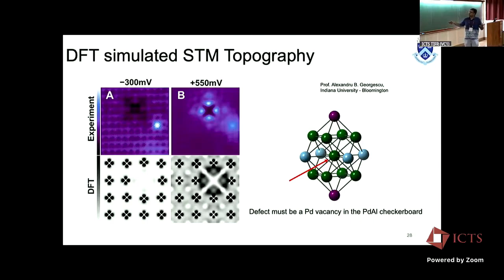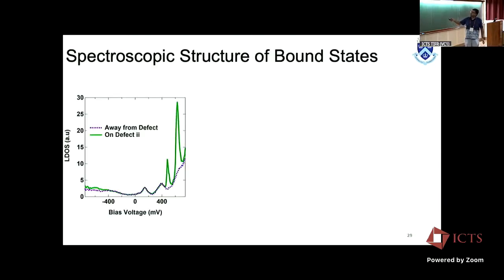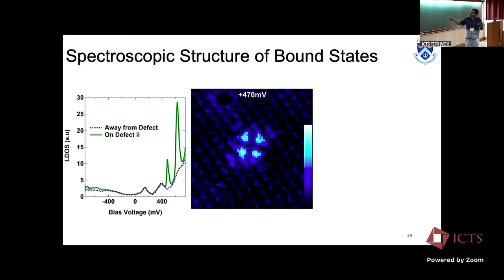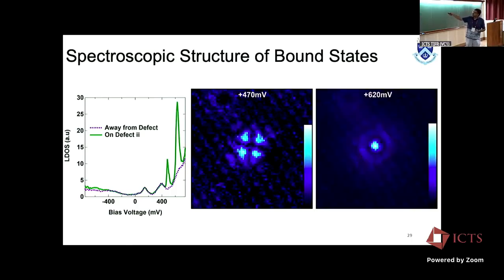And so what this defect is, it's a vacancy in the palladium site, and this is something we can confirm with DFT. And now that you have understood the physics of this bound state, you can understand the structure of this. This is precisely the structure of that compact localized state that avoids the impurity site. That's this one. And there is a second one where all the dangling bonds from the sides get together and are enhanced at the impurity site. And that's at a higher energy, as you might expect. And that is precisely this site. So that's how we understand these states. These are actually compact localized states, which you are visualizing because you put a defect into a geometrically frustrated lattice.